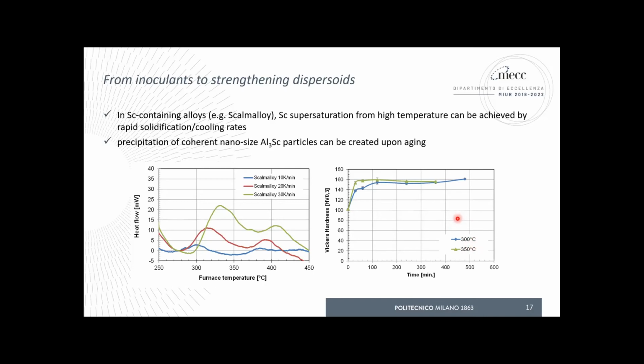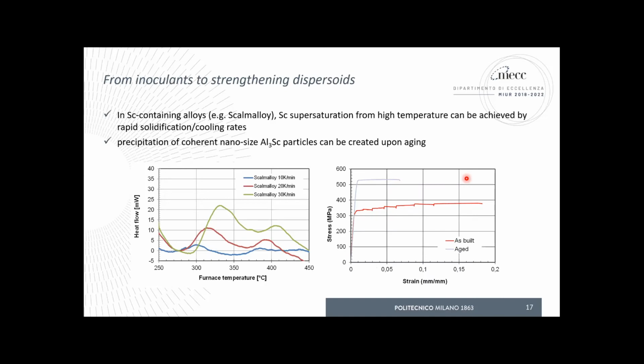Here, on the right side, there is information about the hardness curve that can be achieved during the aging of laser powder bed fusion processed alloy. The scalmalloy alloy, for instance, is a typical alloy that uses this kind of strategy. And here is a comparison between the stress strain curve of the material processed by LPBF in as-built conditions, so no heat treatment, and aged, showing a significant strengthening effect.